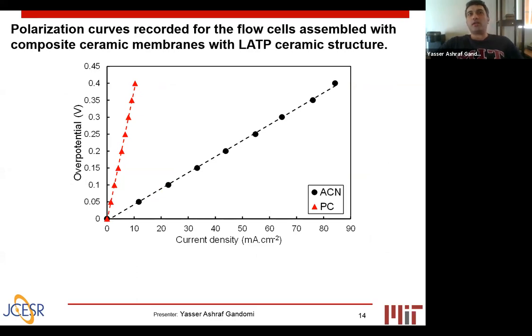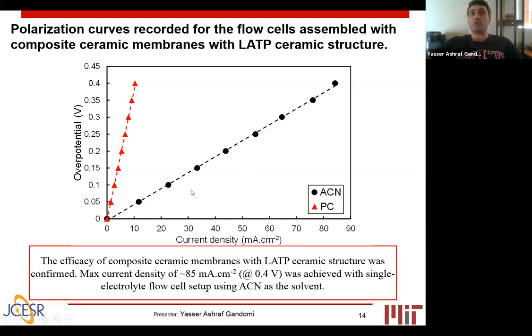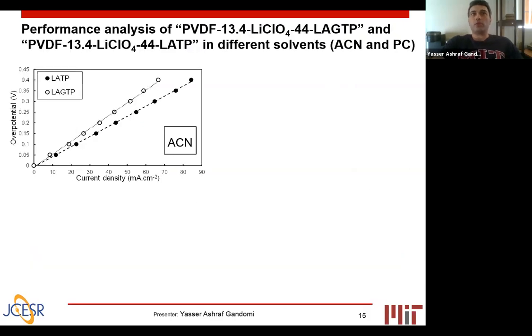So the first data I'm showing you is a polarization analysis. I ran the battery from 0 to 0.4 volt. I recorded the performance, or the current density, as the outcome of the battery. As you can see here, we could achieve up to 85 milliamp per centimeter square at 0.4 volt as the overpotential with the acetonitrile and about 10 milliamp per centimeter square with the propylene carbonate, and an almost linear trend confirming almost negligible mass transport overpotential.